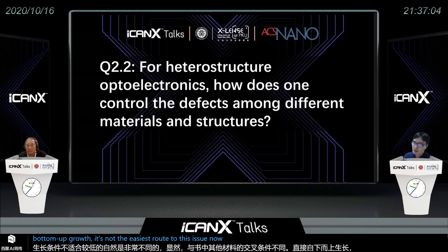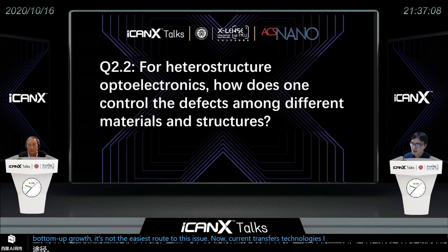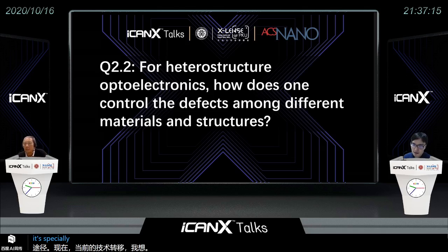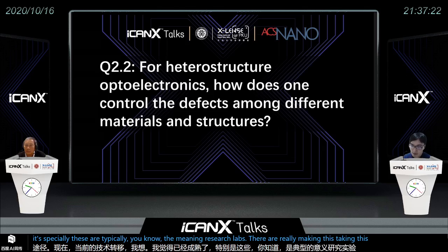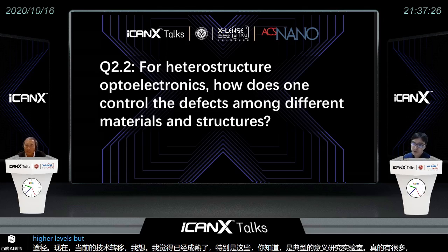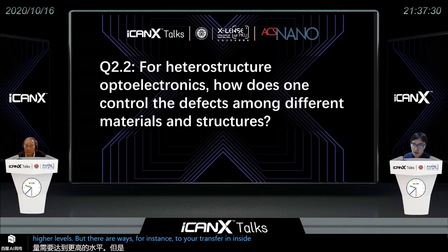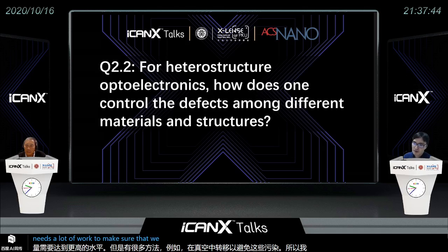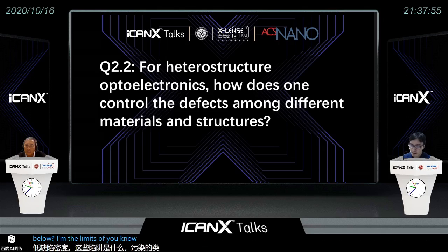Now, the current transfer technologies, I think, are getting mature, especially since the leading research labs are taking these transfer techniques to higher levels. There are ways, for instance, to transfer inside a vacuum to avoid these contaminations. But I think that still needs a lot of work to make sure that we can reduce the defect density, or the trapped contamination type of defect densities, below the limits needed for some device applications.